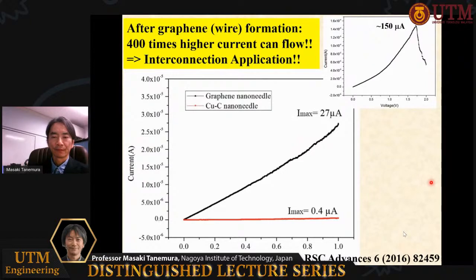This is also the current voltage characteristics before and after the formation of graphene nanowire. Before the graphene nanowire formation, the obtained current was about 0.4 microampere. But after the graphene nanowire formation, about 27 microampere was achieved, and about 150 microampere was achieved by further increase in voltage for only one carbon nanofiber. We are now planning to use this for the interconnection application.